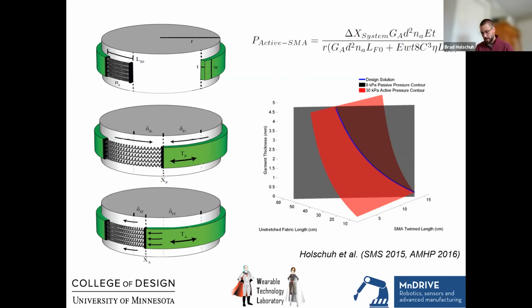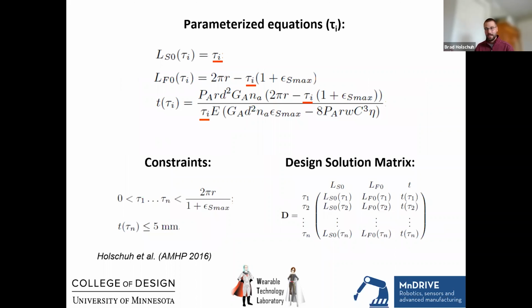So this is some work that we worked on right at the end of my graduate career, 2015, 2016. And so we built a bunch of these systems, and we also went through the effort to try to analytically model them. Right? We don't have time to go through all the details here, but what you see here is a predictive equation that lets you manipulate a bunch of the system parameters with respect to the fabric and the actuators and the radius that you're wrapping around, et cetera. And you can model the amount of force and even do optimizations for different design requirements, which is what you see in the 3D plot there, to create different performance metrics for a soft tourniquet or a soft compression garment in this case.